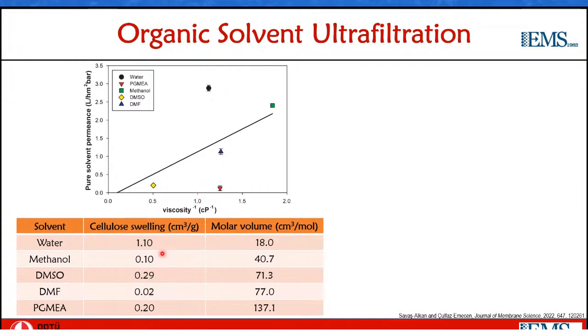The reason we think that water has a higher permeance than would be expected from pore flow is that it swells cellulose to a much more significant extent compared to the other solvents. And a higher extent of swelling means a higher solubility of the solvent in the membrane matrix. And when we consider that pore flow and solution diffusion mechanisms could be acting simultaneously, this large extent of swelling of cellulose could be increasing the pure water permeance of these membranes to a value that is higher than would be simply expected by pore flow. When we come to PGMEA, what is likely happening has to do with the much higher molar volume, so much higher bulkiness of this solvent, and possibly steric effects at the pores.